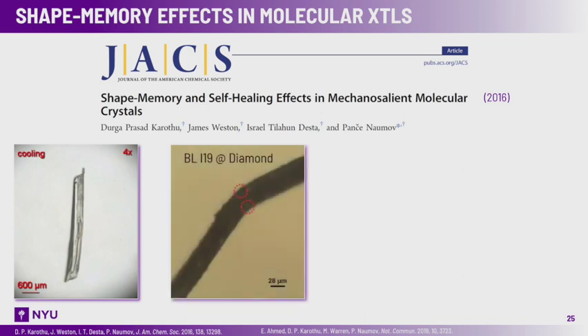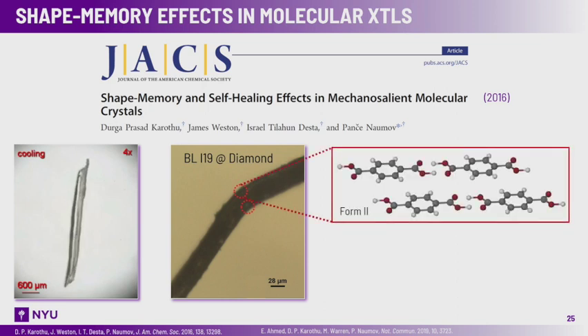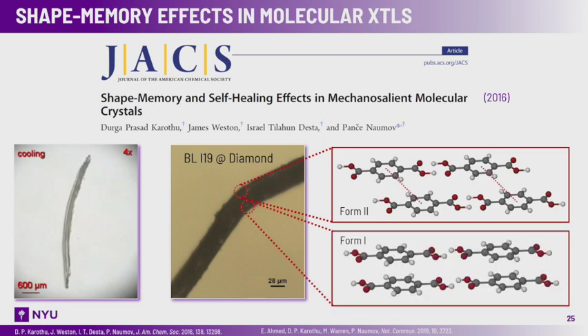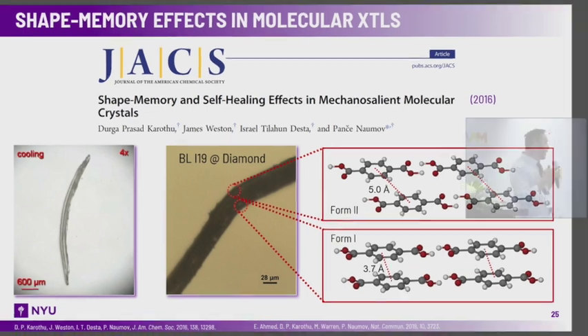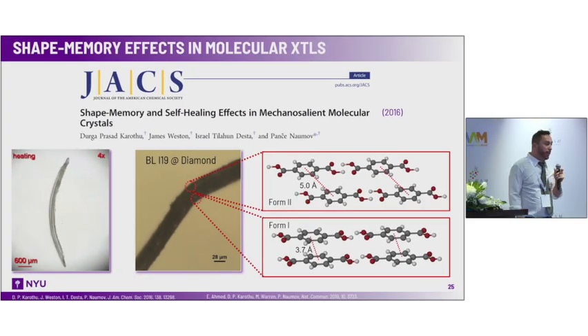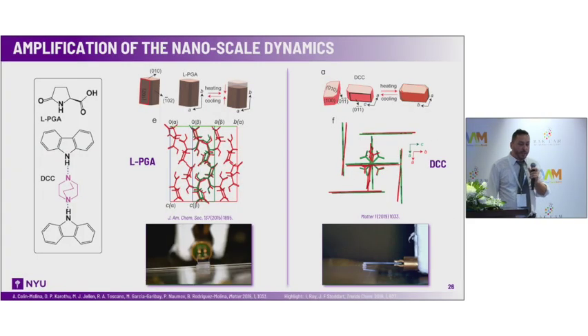So what is happening here? We had to resort to synchrotron radiation and X-rays at Diamond to determine the crystal structure of this material, and we find two different forms in two different parts of the material. So basically we have some sort of bilayer that can be switched back and forth, and this accounts for the shape memory effect.